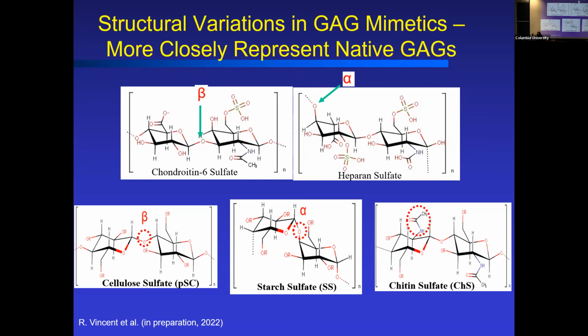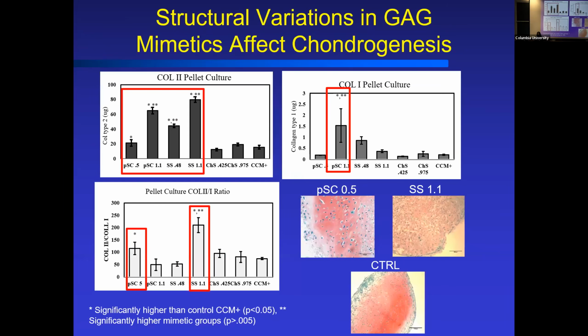So if you look at the structure of the native GAGs shown here, they have amine groups, they have different what we call glycosidic linkages, these beta and alphas, which is just these orientations in the structure. And so we wanted to look at that more carefully. We can create these GAG mimetics not only out of cellulose, but also starch and chitin, and those have different types of linkages or functional groups. We've been showing, at least in some early data, that we are promoting chondrogenesis using those other types of GAG mimetics. And so this is exciting, and we're trying to see where this will take us.